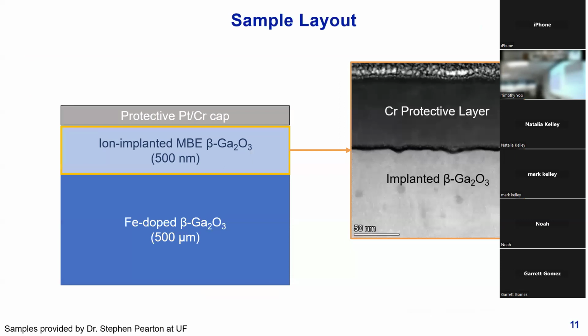And so here's our sample layout. We have a fairly simple structure here. It's just the beta gallium oxide substrate with the film. This film is going to be implanted, and we're going to be looking at roughly the top half surface of this film here. And there's a protective platinum and chromium cap to help preserve that surface structure.